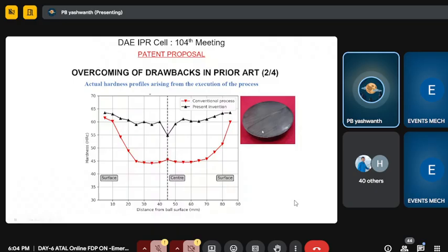You can see this is the size of the ball. You may see the flat face because a small slice has been cut and it is being studied for the hardness. When we do a conventional hardening process on the surface, we can achieve a hardness of 60 HRC. You all know it's a bulk hardness, where HRC is Rockwell. In the periphery on the left side and the right side, there is no problem in the surface. But as we move to the core zone, you have a sharp depletion to 45, 43, someplace 44. So the red one is the actual conventional process in which the bearing is treated. Actually, we have the problem that the core becomes very soft. So the design engineers demanded that we deliver a core which has a minimum of 55 HRC. So in the center we need to achieve this.